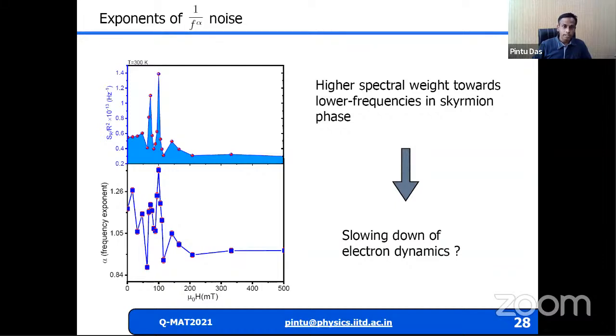Of course, with the current density that we have applied, the skyrmions are supposed to be in the static phase. So there is no skyrmion motion as such that we are expecting in this current or field regime. Nevertheless, we are seeing this kind of evolution of the charge carrier dynamics, the electron dynamics, in the skyrmion phase.